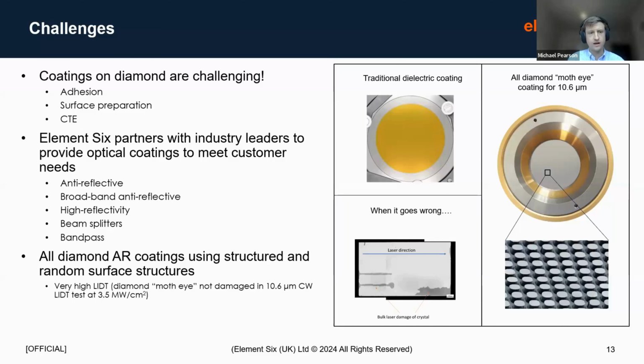That said, we do have a lot of experience working with partners, and over the last sort of 10 years, we have produced a range of coatings, everything from single wavelength anti-reflective coatings to dual wavelength anti-reflective coatings, broadband, high reflectivity coatings, beam splitters, and bandpass filters. So we do have experience, but typically, if you want a new or slightly unusual coating, there is a period of development that is needed in order to optimize the coatings to your application.